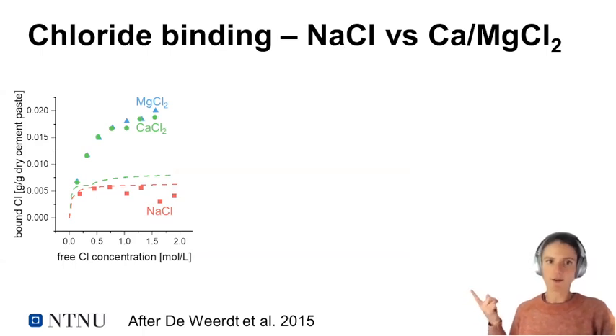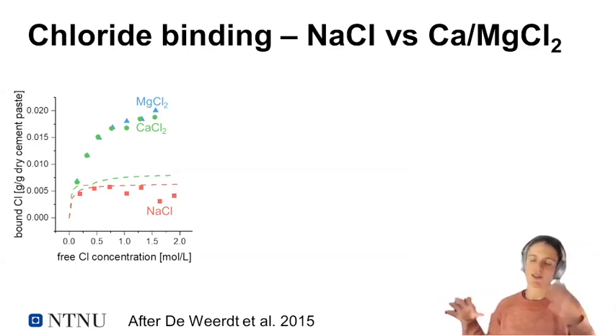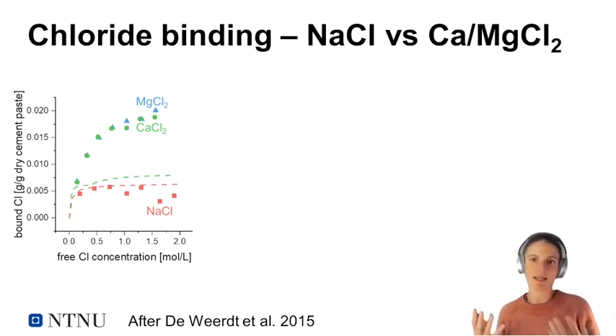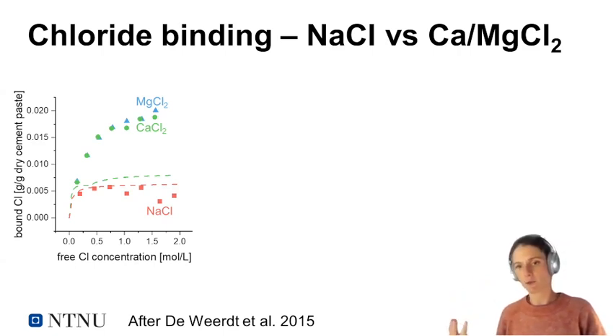The graph I'm showing here shows you on the vertical axis the amount of bound chlorides, so how much chloride your cement paste can take up, and on the horizontal axis it shows you the chloride concentration this cement paste is in equilibrium with. You can see that there's a very large difference, definitely when we look at chloride concentrations higher than 0.5 mole per liter, between sodium chloride and calcium or magnesium chloride.